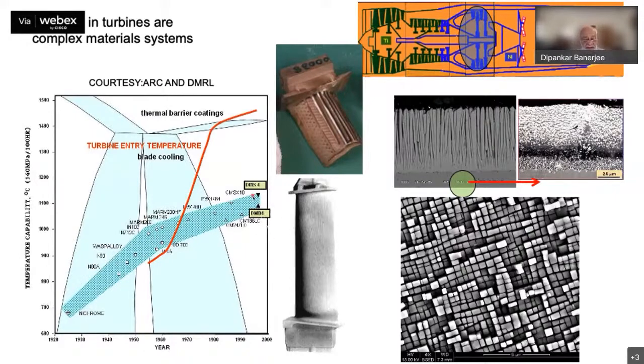Okay, so the temperature capability of today's nickel-based alloys is around 1100 degrees centigrade. The turbine entry temperatures in today's engines are about 1600 to 1700 degrees centigrade, and actually are above the melting point of the material, which is typically around 1400 degrees centigrade. So how do you use a material which has a capability of about 1100 degrees centigrade, which itself is a reasonable fraction of the melting point, but there is this huge gap which we have learned to overcome.